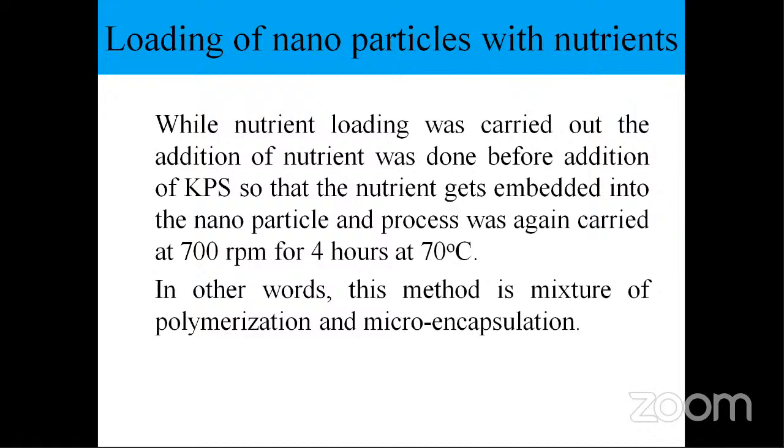The first trial was with basically preparation of nanoparticles. Now I have to prepare nanofertilizers. For that, you have to load the nanoparticles with the fertilizers. Basically, prior to KPS addition, we added nutrient, so that the nutrient gets embedded into the nanoparticles. When KPS was added, it helped to produce the nanoparticles. But prior to that, we added nutrient into the solution so that the nutrient gets embedded onto the chitosan chains.